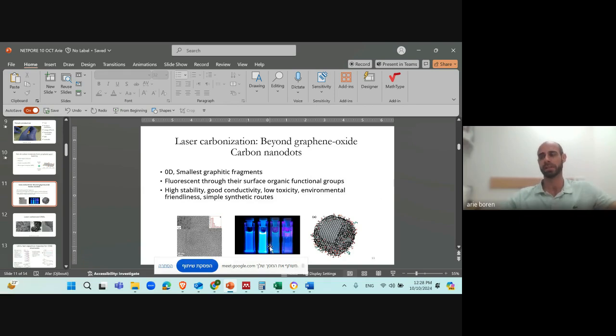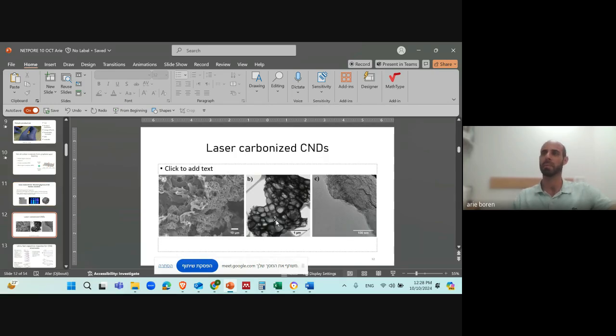They are fluorescent because of the functional groups on the surface. So they could be very good candidates to undergo the laser reaction. And indeed, if you put them under laser, you will get graphene films. But look, let's say the macrostructure, the morphology of these films are very different.